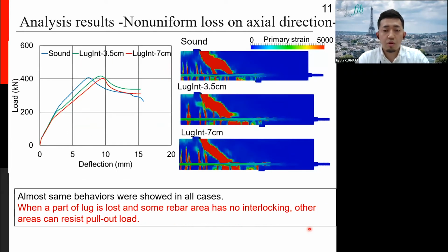The last point is the non-uniform loss in the axial direction. Looking at the load displacement curve, a slight rigidity decline occurred, and its starting point became lower with the increment of intermediate length. However, the rebar slip behavior or the behavior change seen in the former bond deteriorated cases were not observed in either case. So from this result, when a part of the lug is lost and some rebar area has no interlocking, if the other area has a sound interlocking, this part can resist the load, and in the overall beam, the bond can be maintained.